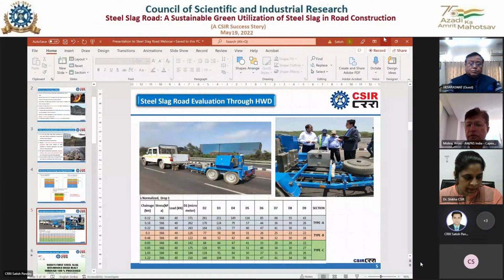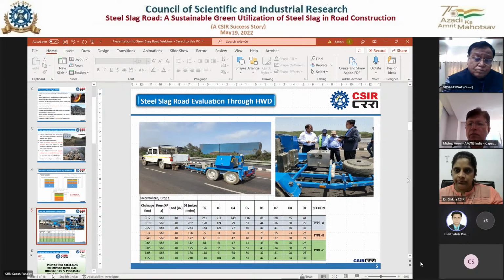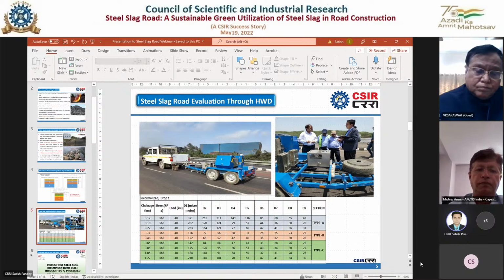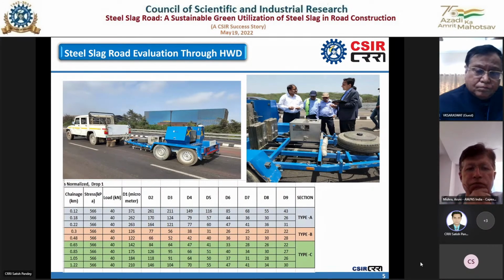There is a breakdown in the internet connectivity. So in this particular photograph, you can see that the heavyweight deflectometer evaluation is carried out on steel slag road test section. We tested this road as per the IRC parameters, and at 40 kilonewton load, you can see the deflection in the road which has been built through natural aggregate is around 371 to 260 micrometer. But in comparison, in the road which has been built with 32% reduced thickness, there is a significant reduction in the pavement surface deflection by 50 to 60%.